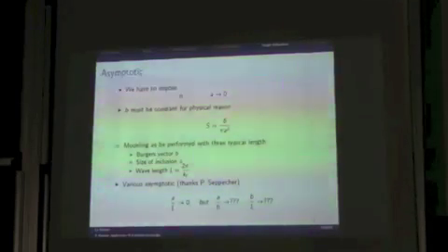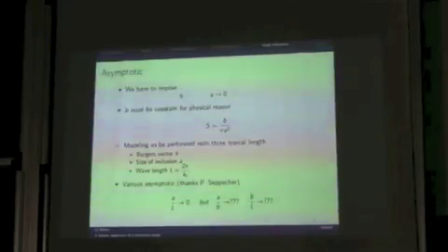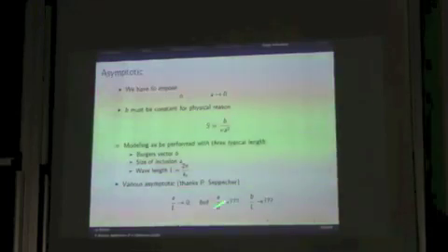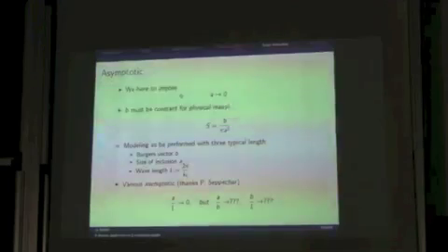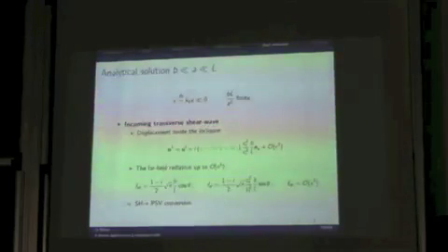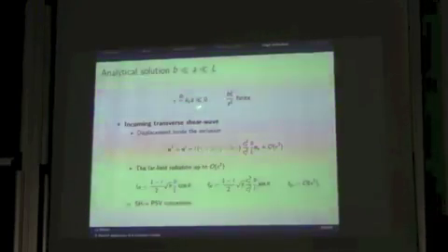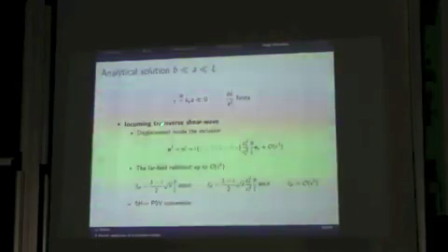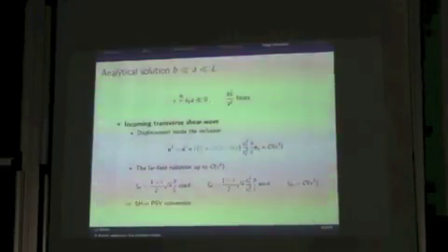So we have a modeling which is related to three lengths: the length of the Burger vector, the size of the dislocated domain, and the wavelength here for the shear wave. And so, in fact, I impose this typical ratio going to 0, but I do not know what about the other ratios which are possible. So I have solved for you one situation where this ratio is going to 0, this one is going to 0, and this one is finite.